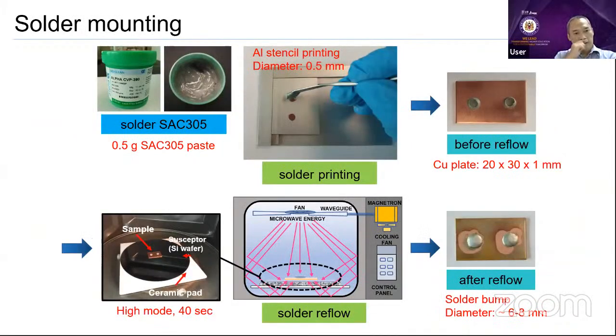This one is the solder mounting for checking the wetting and so on. So this is the solder paste, and we can see the paste here. And this is the way we prepare for the stencil, because we just want to get a very nice small sample on the copper substrate. This one is before reflow, and then we put it inside the microwave. These are ceramics, these are silicon wafers, and this is our sample. And then we run the reflow.